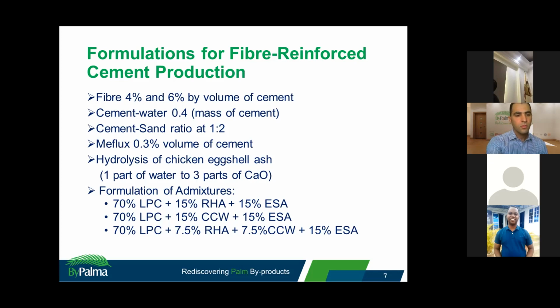When you hydrolyze the calcium oxide, you are going to get calcium hydroxide. And calcium hydroxide is a good product in chemical reaction with cement. That's what led to some of the improvement we are going to see in the results very soon. Because when you react water with calcium oxide, you get calcium hydroxide. Now, why do I have to do it in 1 part by 3 parts?